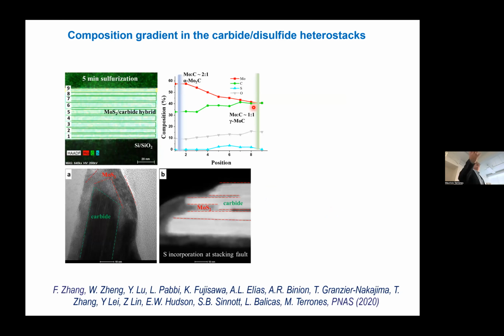Then one of the things, so it was the mechanism. We can see that this is the carbide phase, and this is the molysulfide. We can see stacking faults, and this is what we think. You can see the changing contrast here. You can see the H2S.